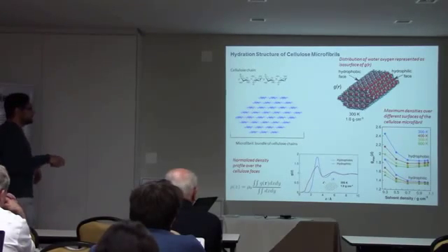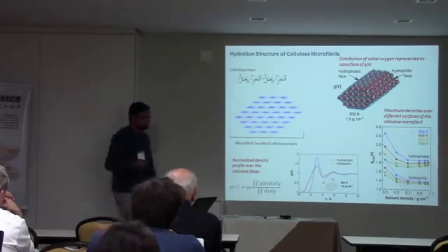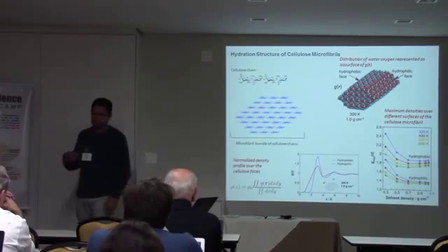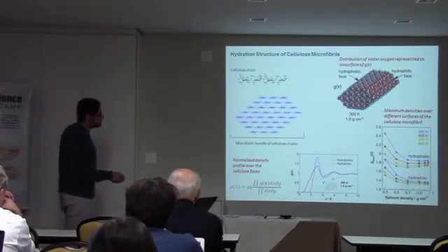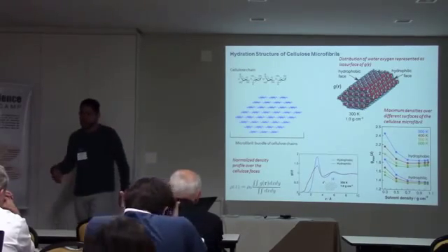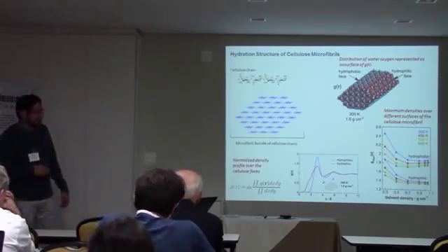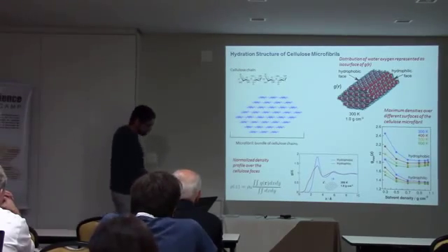These are conditions that happen in pre-treatment, for example hot water pre-treatment and steam explosion pre-treatment. So this graph shows that most of the changes induced by the solvents in pre-treatment will occur at the hydrophobic surface, not the hydrophilic surface.